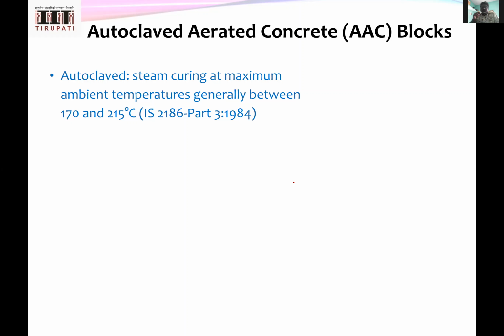Okay, but I have seen one or two people, and even I myself have visited some places, where they have used AAC block as a load-bearing wall. It is not recommendable because in a load-bearing wall you have a heavy load coming in and you have a heavy porous material. So creep will be very high. You won't see that in the immediate time. You'll see in one or two years that a lot of cracks will generate other than these cracks. These cracks are just atmosphere changes creating these issues, right? But other cracks are due to sustained loading, which is not actually acceptable.